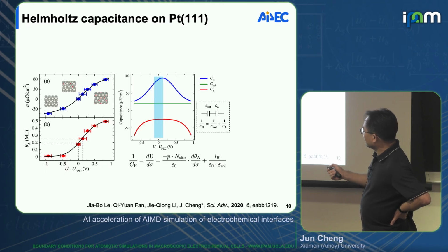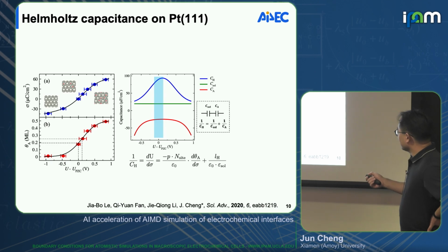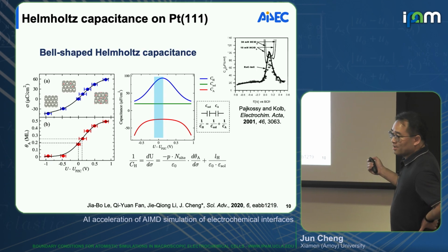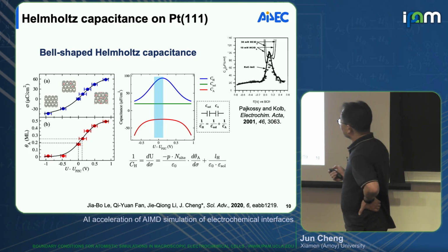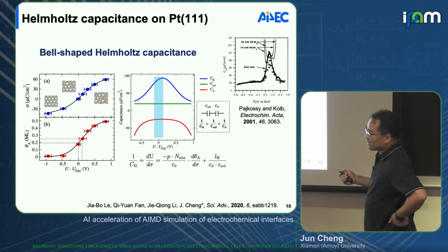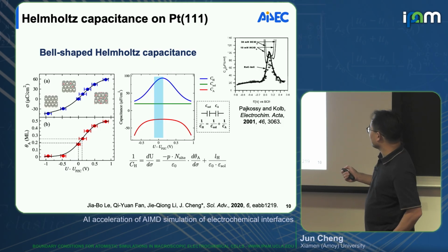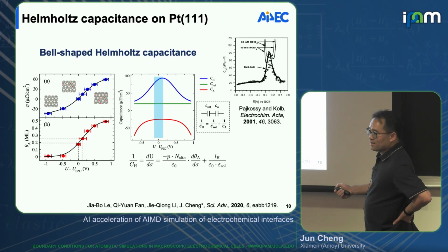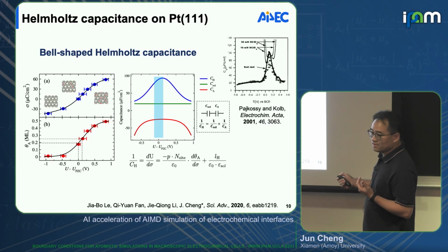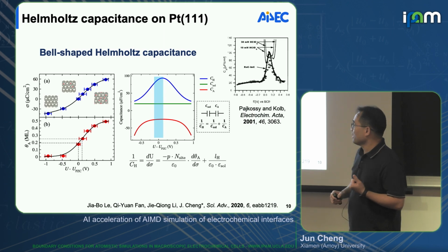Then if we take the derivative of this charging curve, we get this differential capacitance, this bell shape that exactly reproduces what is experimentally seen here. So this Helmholtz capacitance can be understood by, again, separating the effect from the normal water orientation, rather standard one, and also the chemisorption. This Frumkin-type adsorption isotherm can actually give you a negative capacitance. So those two connected in series will reproduce this bell-shaped Helmholtz capacitance.